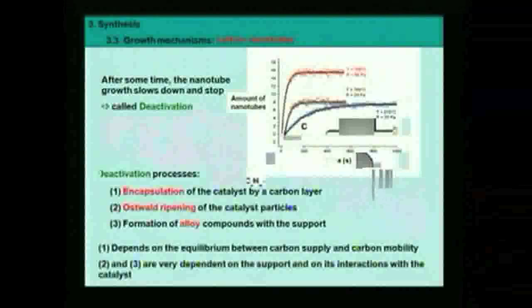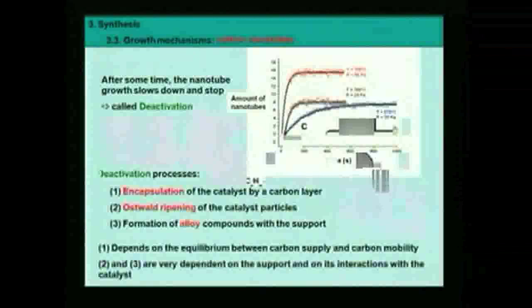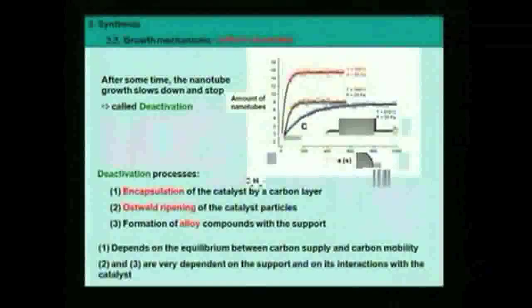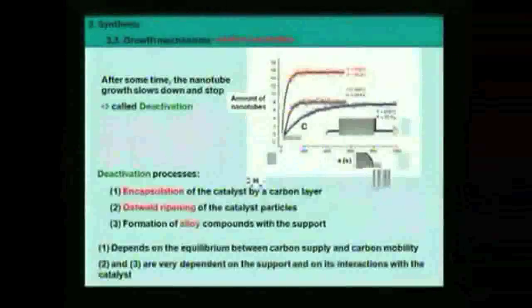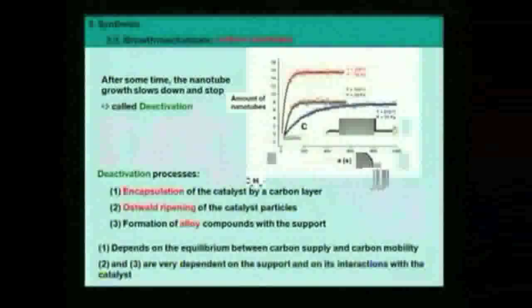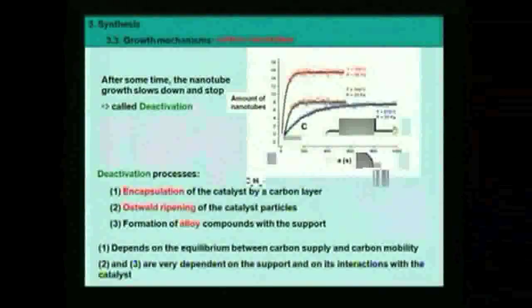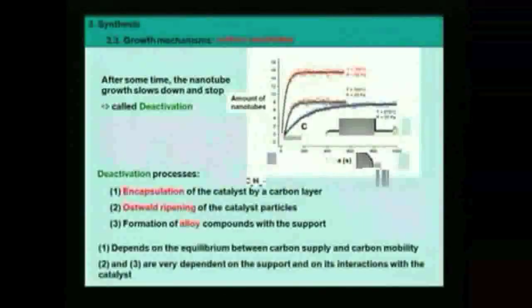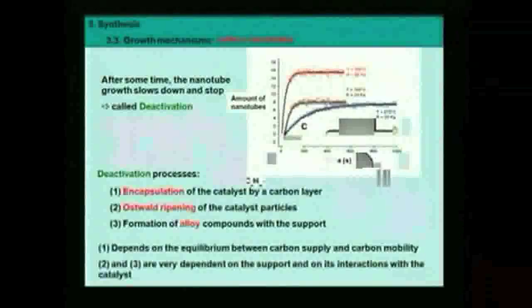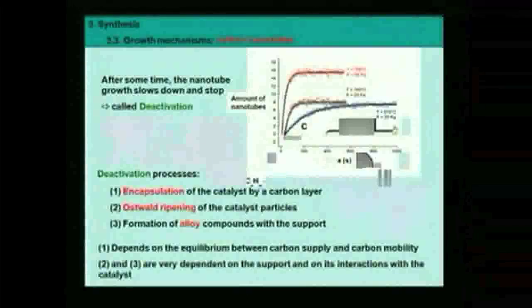I mean that if we form too much carbon quickly, this carbon, instead of going away from the particle like a nanotube, could grow around the particle and encapsulate it. And then the catalyst is poisoned because there is no available surface. The surface is not available for new molecules to adsorb. The surface is covered. It's unreactive. This is the first case of deactivation, encapsulation.